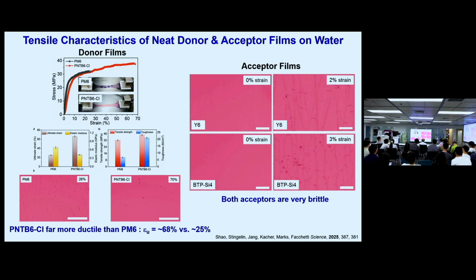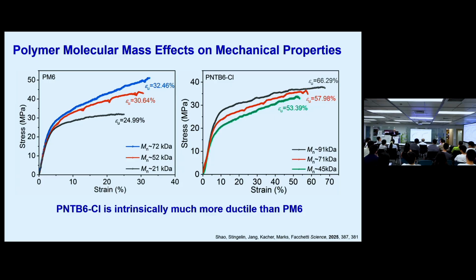But when we make the blends, these mixtures of the strands of spaghetti, something dramatic happens. So this is just showing also, we'll get to that in a minute, molecular weight of these different polymers and at which point they break. And so you can see here, the one that has the highest molecular weight can be stretched the most before it breaks. And these are with PM6 donor polymer, and this was with the chlorinated one. Okay, so nothing there looks really so unusual or exceptional.